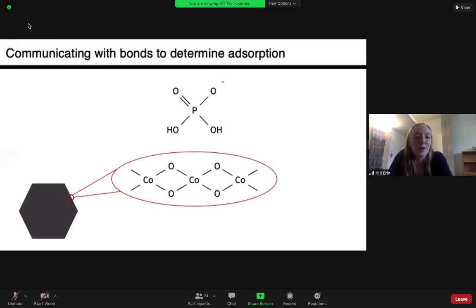All right, so here we have our little LCO hexagon plate. It's about 10 nanometers across and 5 nanometers deep. And if we blow up this surface, we see this repeating structure of cobalt and oxygen. This is the surface that our phosphate can bond to.